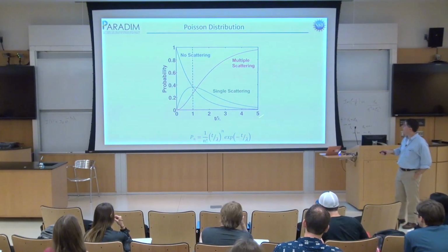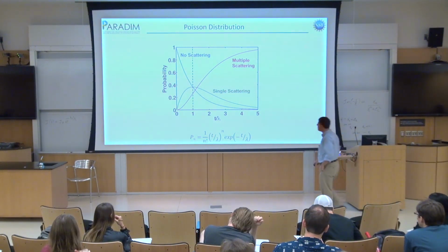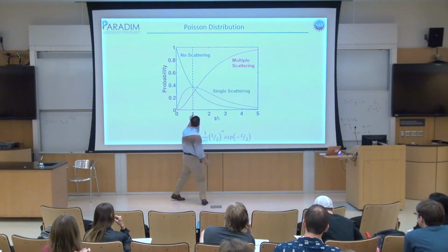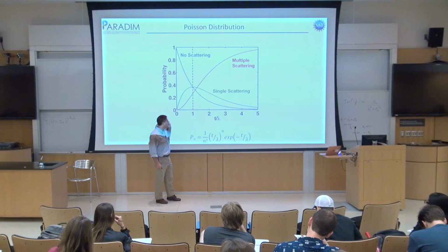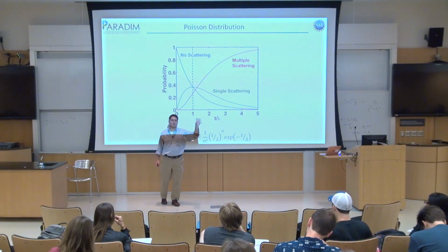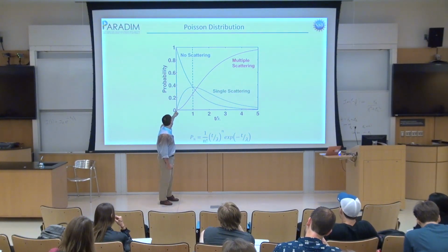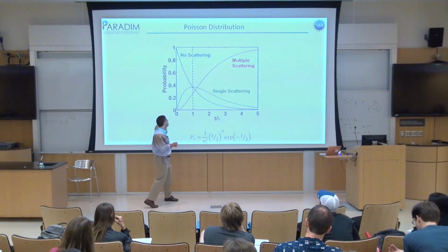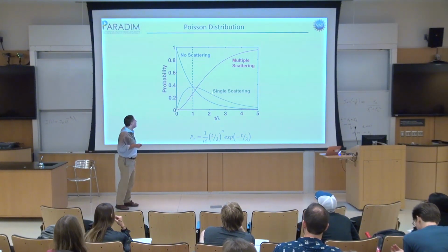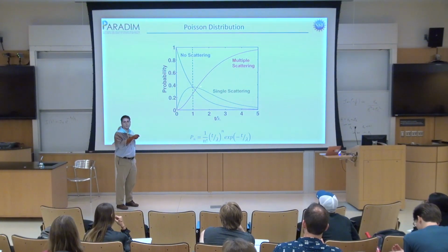And in this case, I'm using this to ask how many plasmon scattering events we're getting. If I want to look at my valence EELS, I want to be tracking and optimizing the single scattering events. So the green curve is the bit that I want, and you can see it's doing nicely at around t over lambda is 1. So that would be the sweet spot.